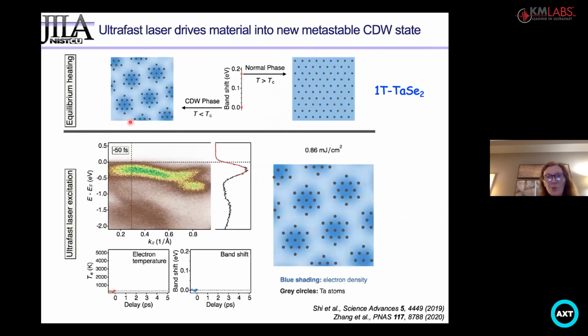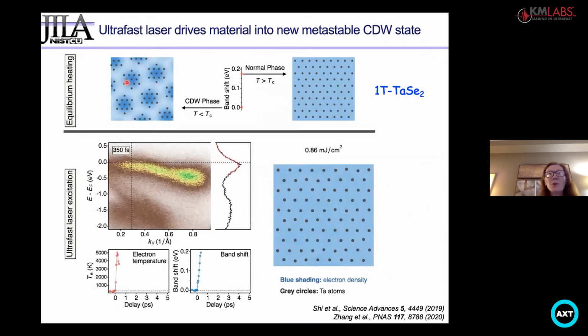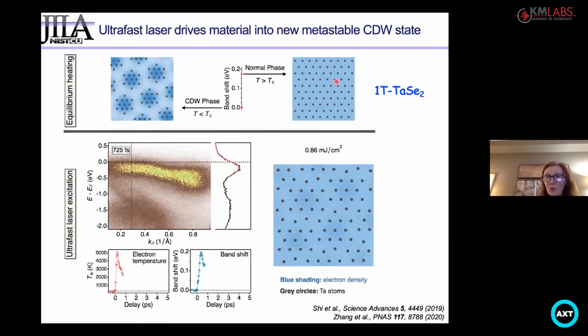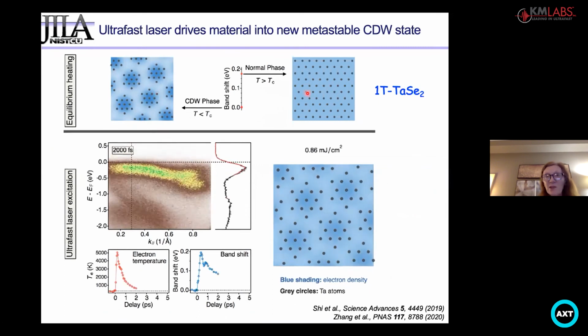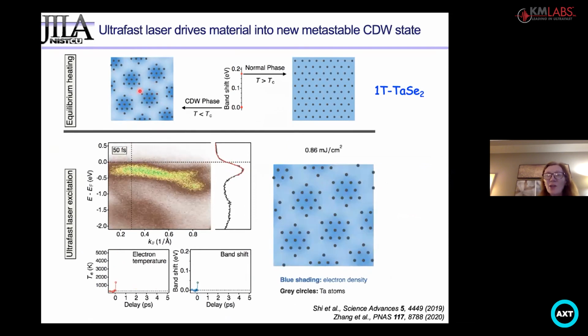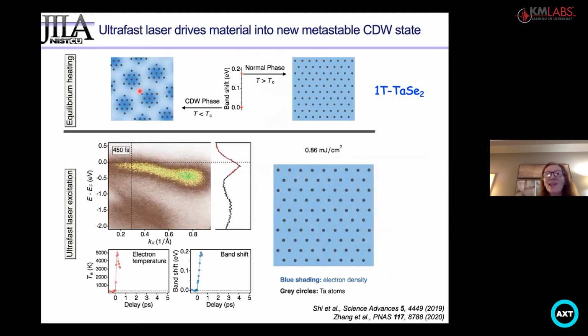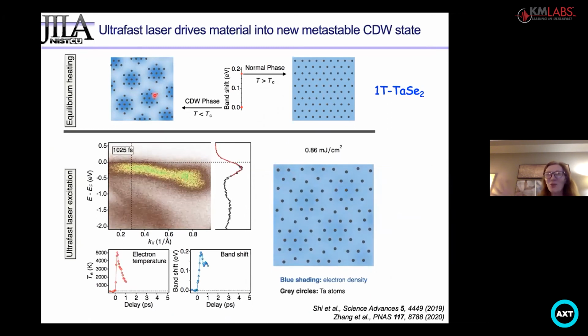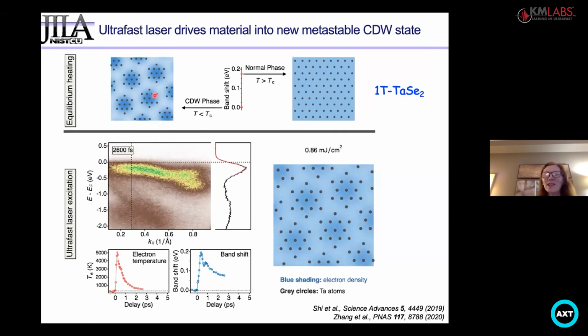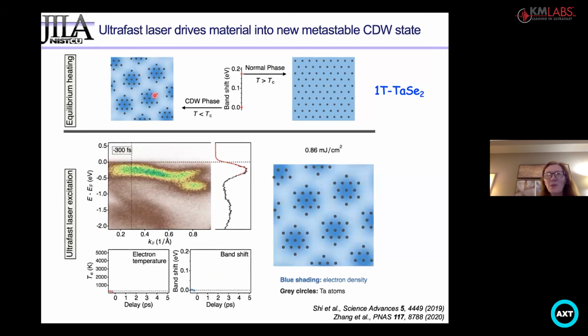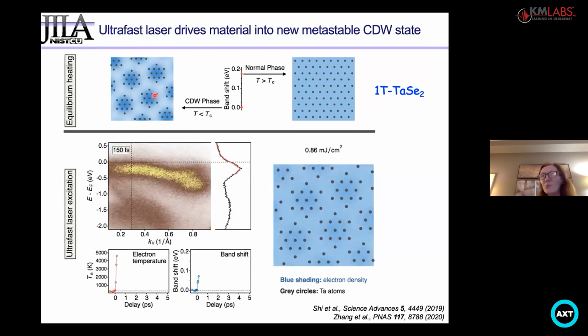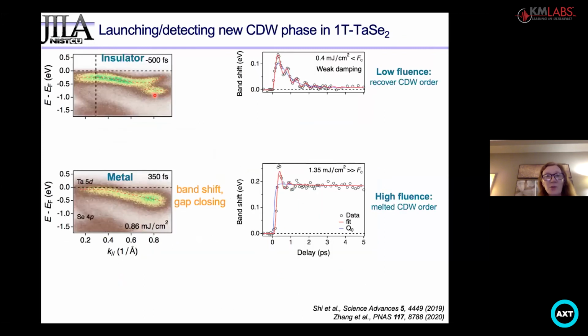What was new is, so in the past, people knew about this charge density wave state and the normal phase and the fact that you could melt this order with a femtosecond laser. What we found is that by smearing the charges, we could actually put the material in any phase in between. Not forever, it lasts only about a nanosecond, but it's still information about the material and about the ability of light to manipulate a material that was not known without using time-resolved ARPES. So this is some of the data.